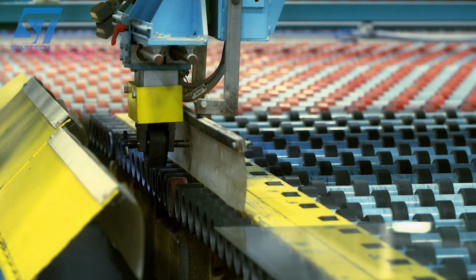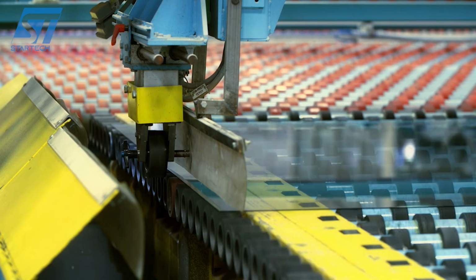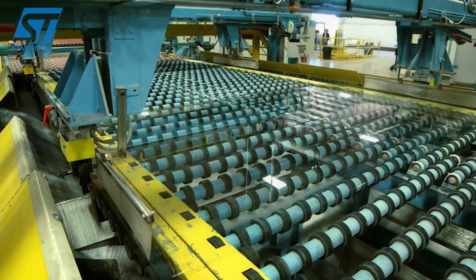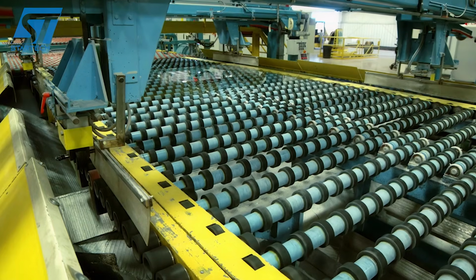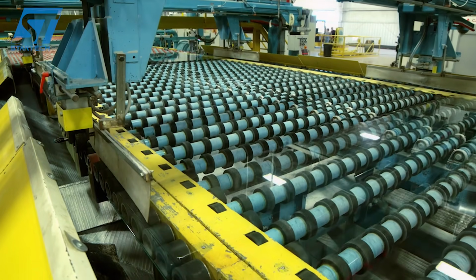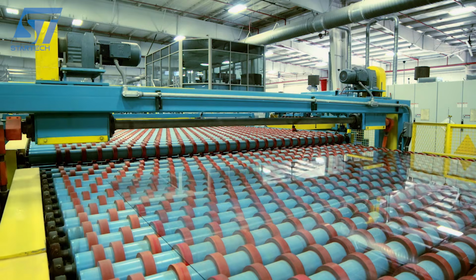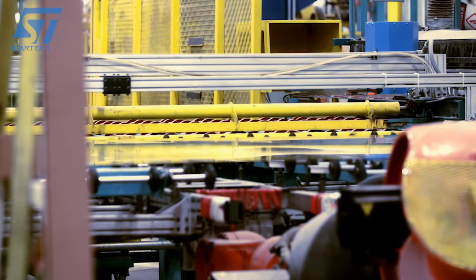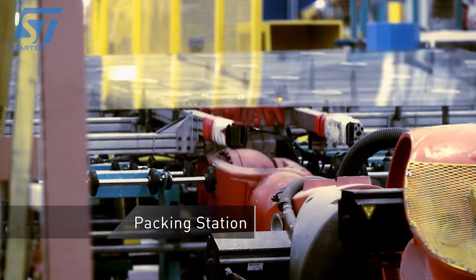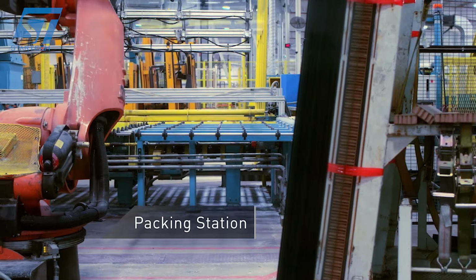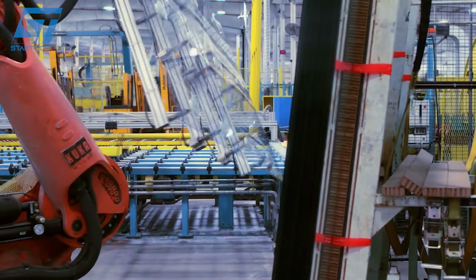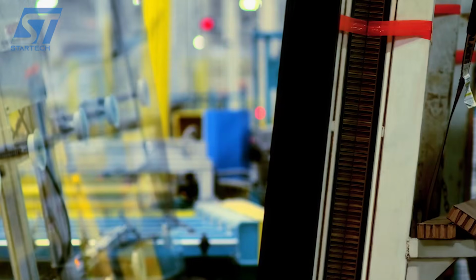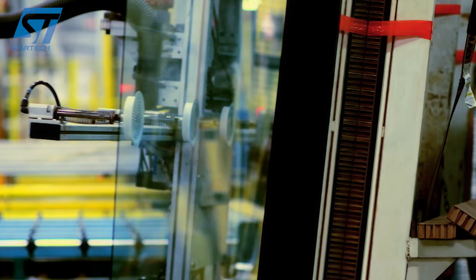After the float bath, the glass ribbon enters the lehr, a long, carefully controlled cooling oven that anneals the glass, relieving internal stresses so it won't crack or shatter. Then it's scored, snapped, inspected, and cut to size by computer-controlled cutting systems. Optical sensors check every square inch for defects, bubbles, inclusions, or distortions. Only perfect glass makes it to the shipping dock.